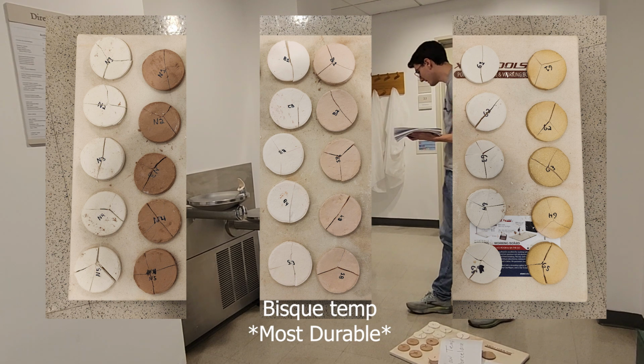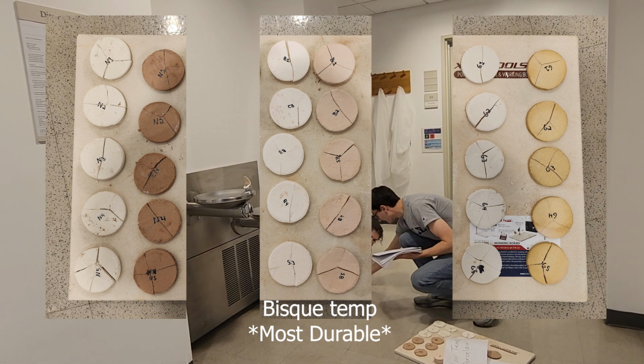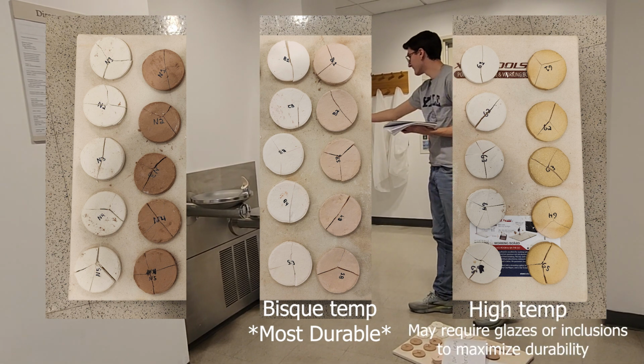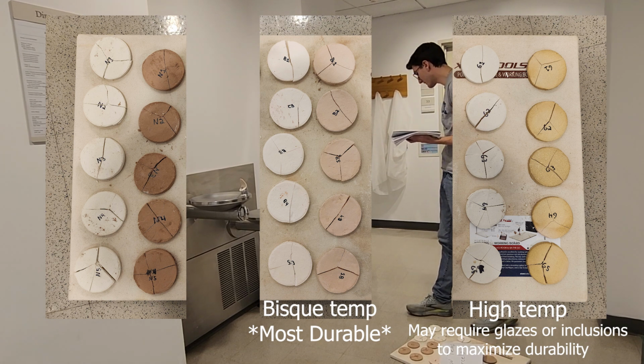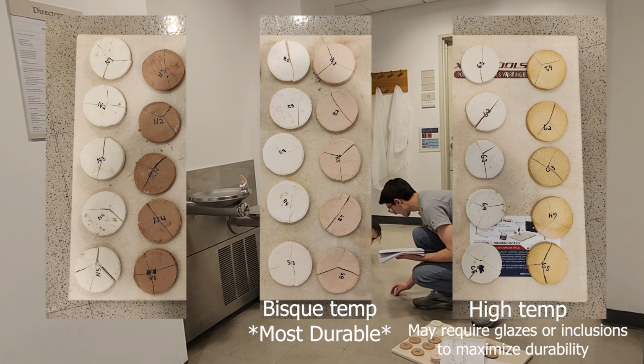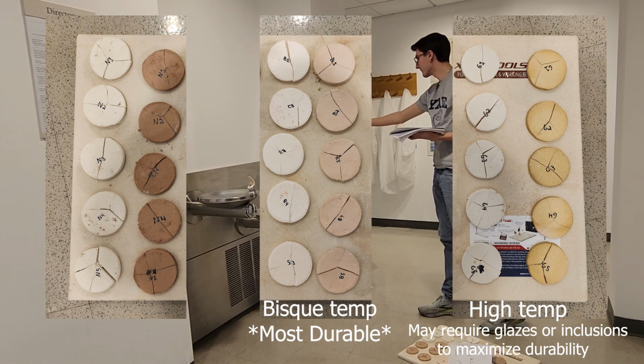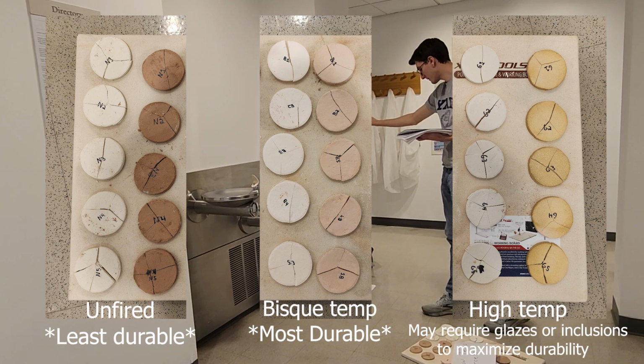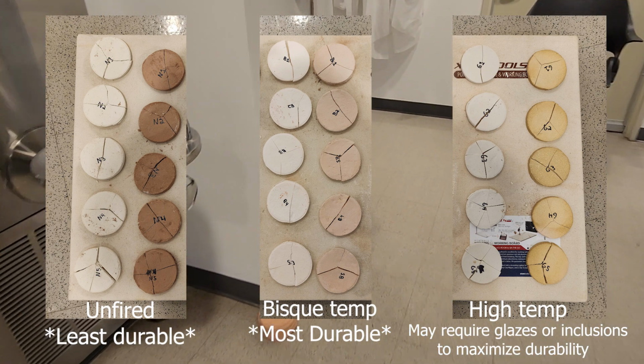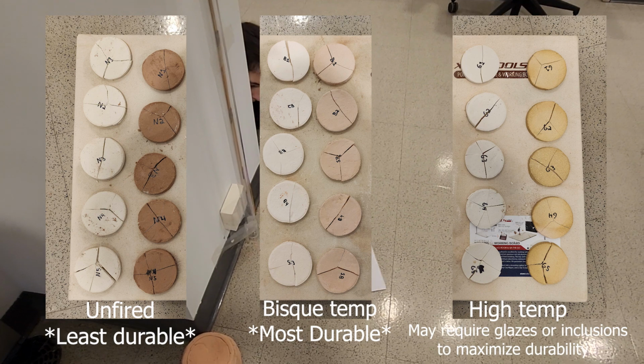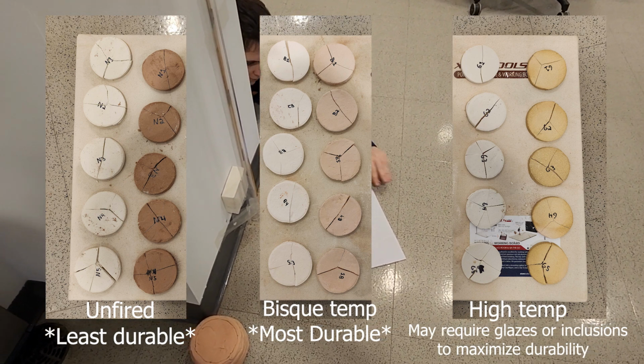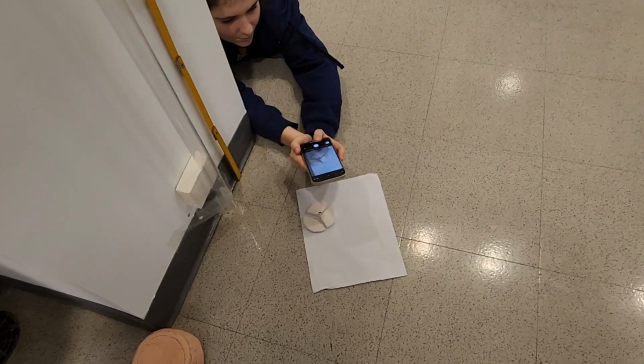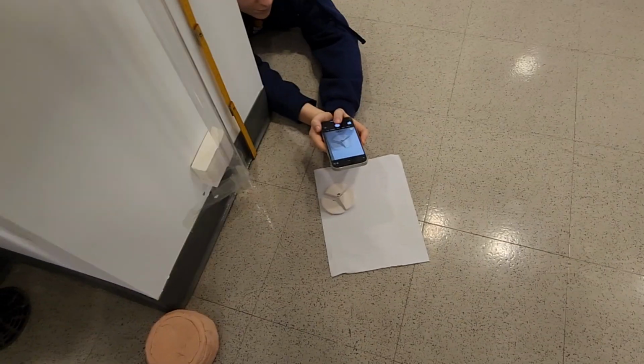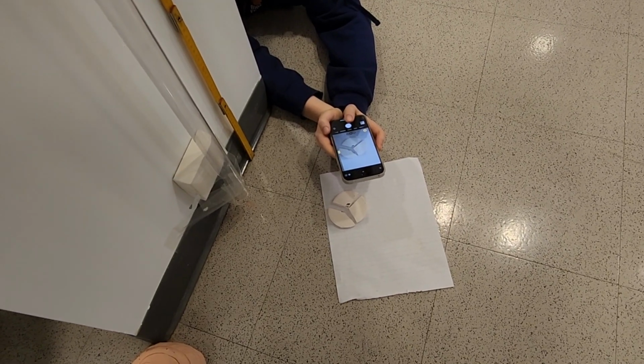While any amount of firing will make a clay more durable, high temperatures, like glaze temps, should probably be used exclusively for clays with glazes or inclusions, such as shell pieces. This tells us that we need to be most careful when handling historical ceramics that are unfired or fired at high temperatures without glazes or inclusions. We can also infer that ceramics we find at research sites that are intact might have been fired at bisque-like temperatures, or were able to endure even more post-depositional disturbance than unfired or extremely high-fired ceramics.